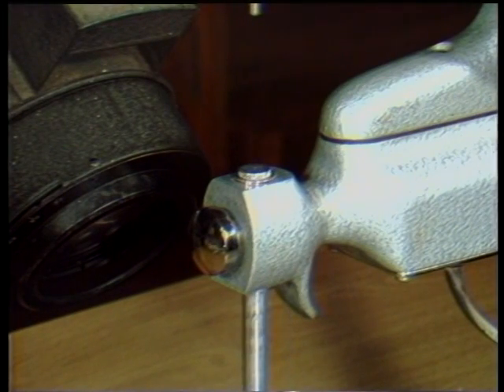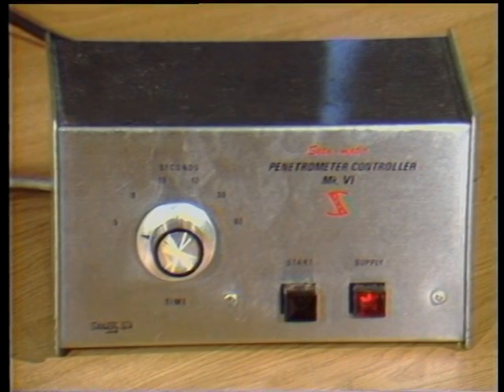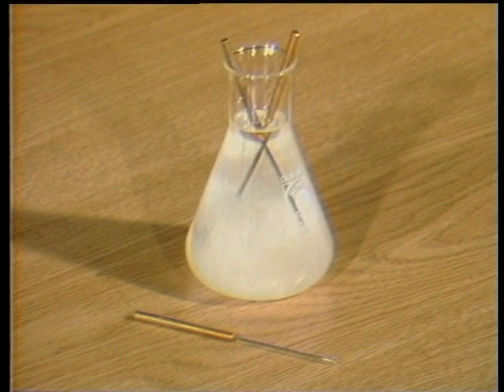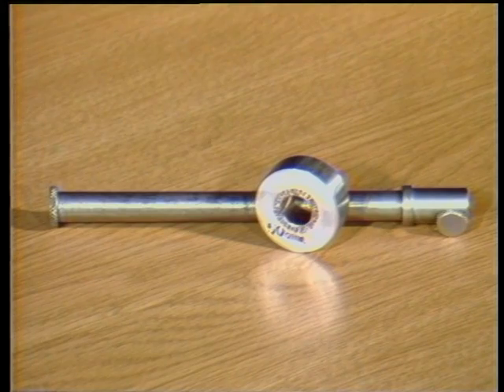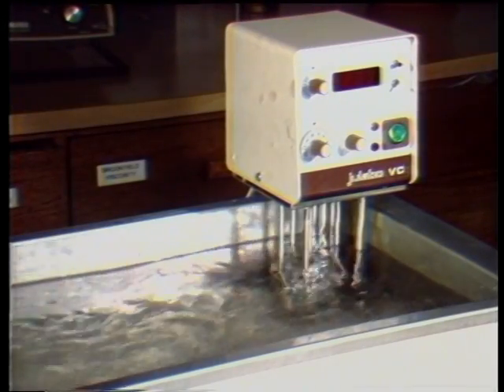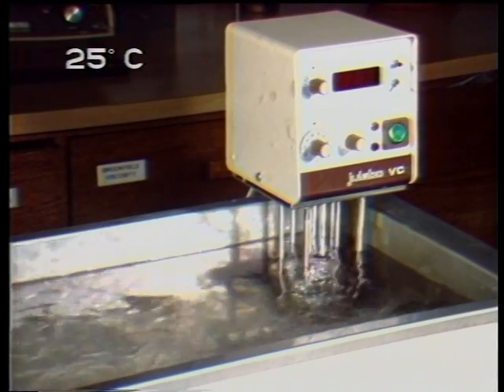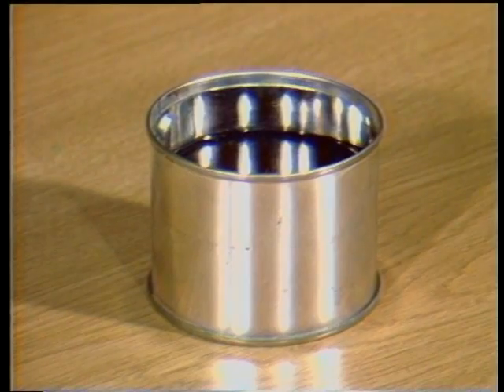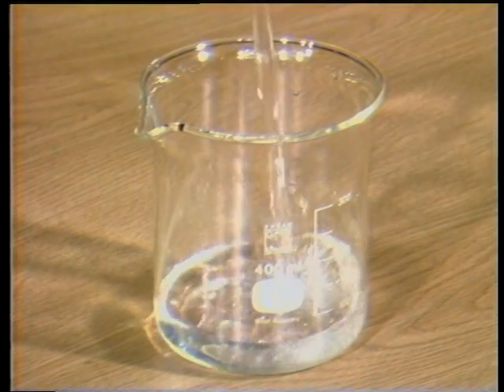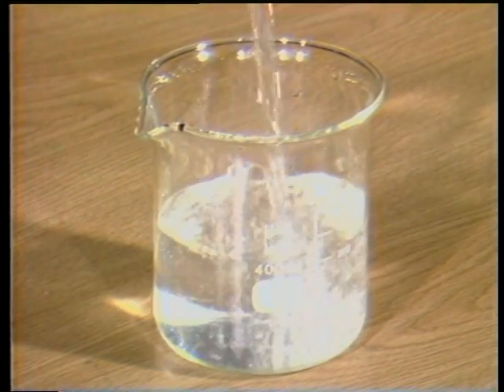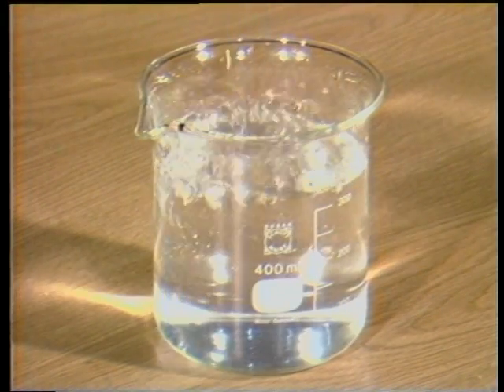A penetrometer that allows frictionless vertical movement of the needle holder. A timing device capable of measuring a 5-second duration accurately. 3 tempered stainless steel penetration needles that meet ISO specifications. A needle holder and weight. A water bath capable of maintaining a sample temperature of 25 degrees Celsius. A specimen container and sample. You'll require a transfer dish having a minimum capacity of 350 millilitres if this experiment is done outside the bath.